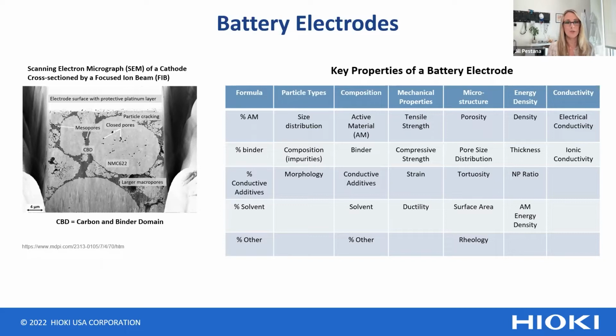Then you have the microstructure, which that picture on the left is a cross-section of a battery electrode up close using scanning electron microscopy. And there you can see a cross-section of those cathode particles. So these are only, it looks like 15 microns in diameter about. And you see the carbon binder domain, the CBD, and the pores inside of this. It's a very complex composite with a lot of different dimensions to it.